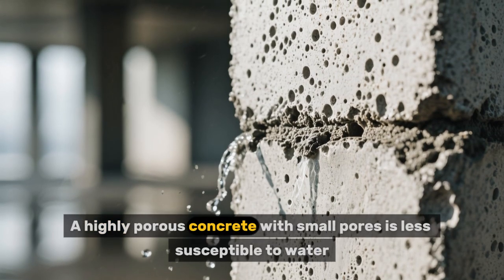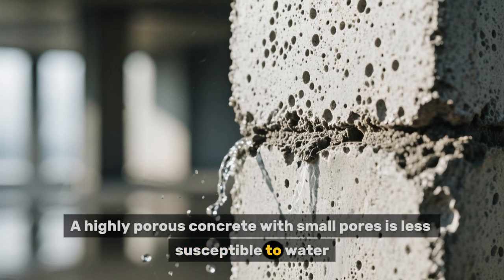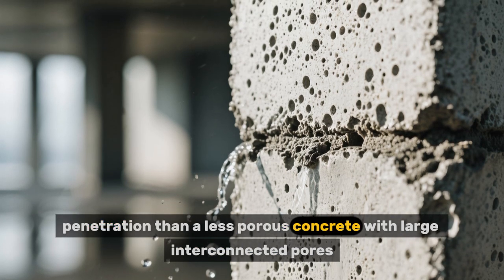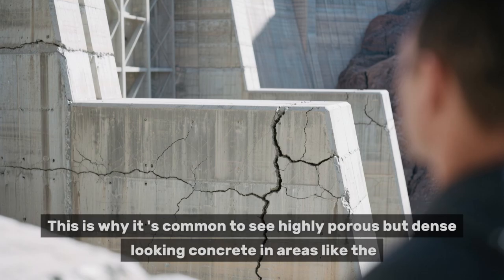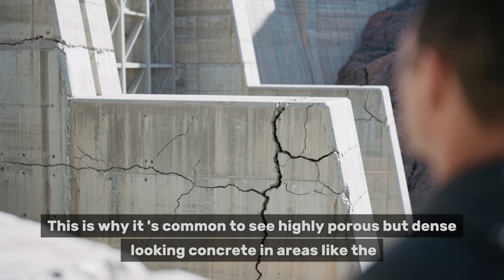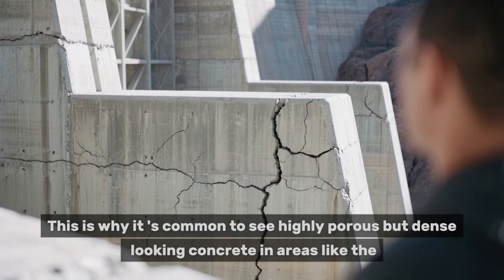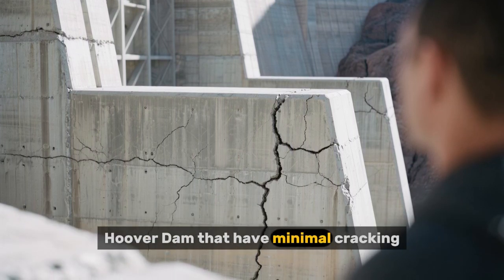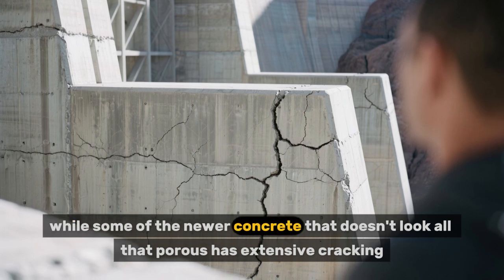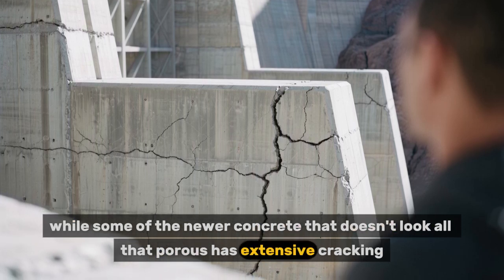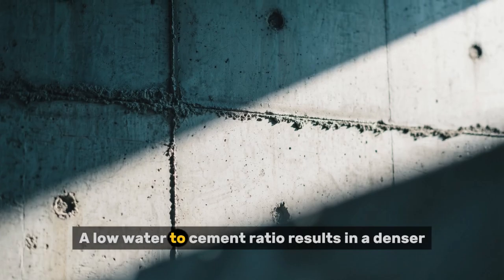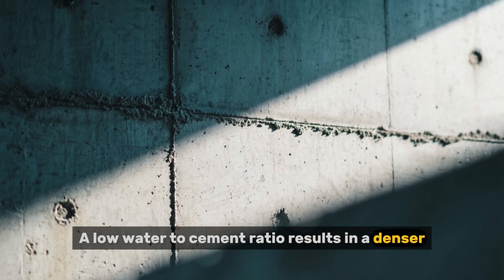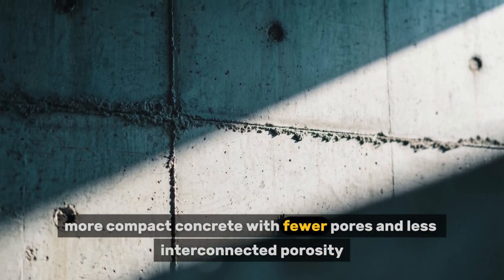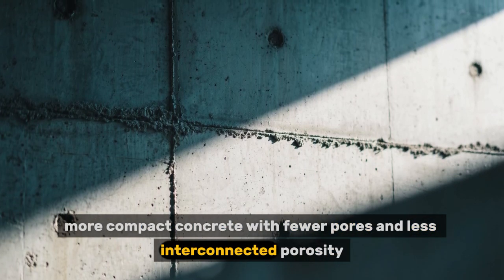A highly porous concrete with small pores is less susceptible to water penetration than a less porous concrete with large interconnected pores. This is why it is common to see highly porous but dense-looking concrete in areas like the Hoover Dam that have minimal cracking, while some of the newer concrete that doesn't look all that porous has extensive cracking. A low water-to-cement ratio results in a denser, more compact concrete with fewer pores and less interconnected porosity.